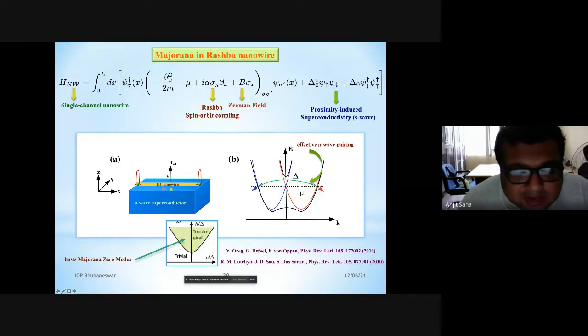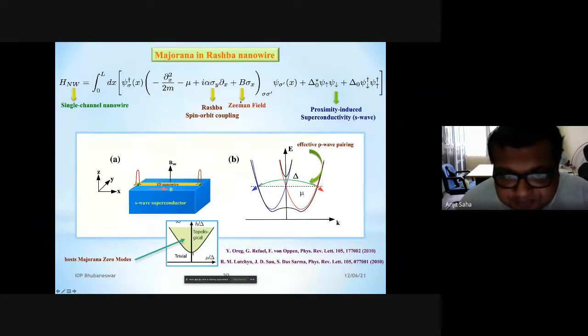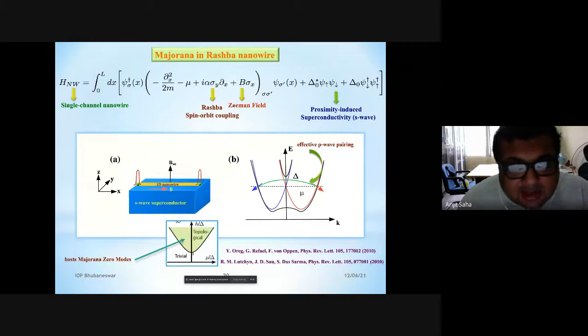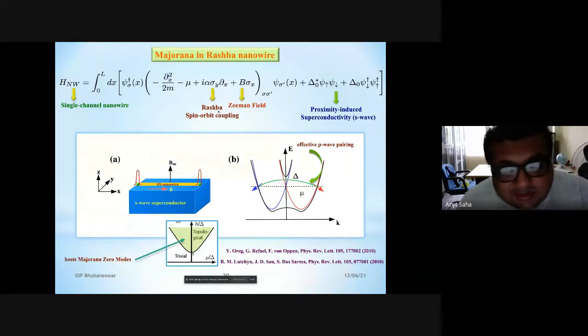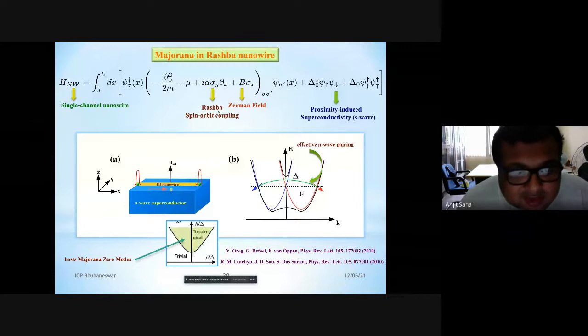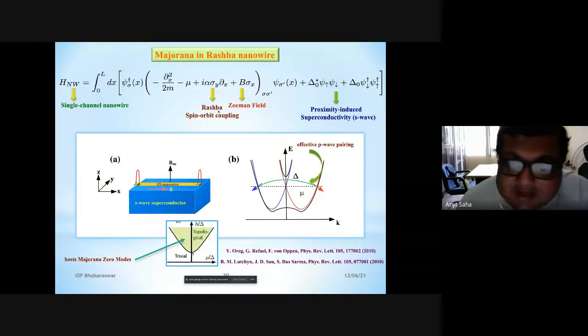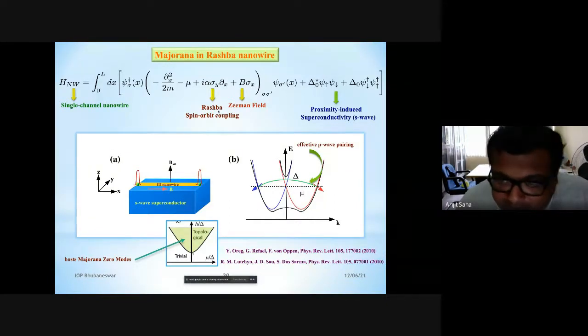And you also apply a Zeeman field, but you apply it such that the spin orbit direction and the Zeeman field are perpendicular to each other. Now, I can choose this nanowire, I can apply a magnetic field, I can take a material for the nanowire with a strong spin orbit coupling. But this nanowire is not superconducting by itself. So how do we bring superconductivity into this nanowire?